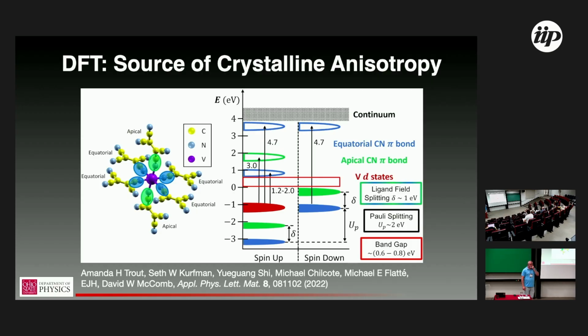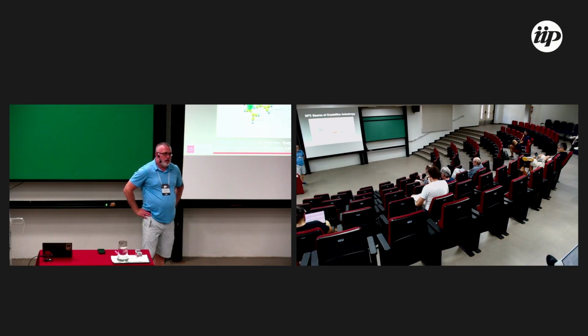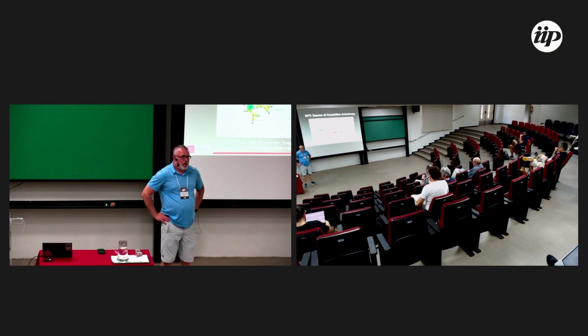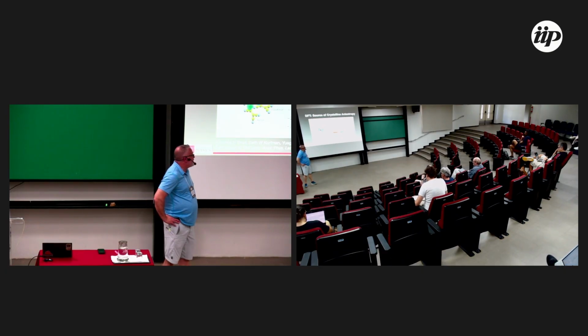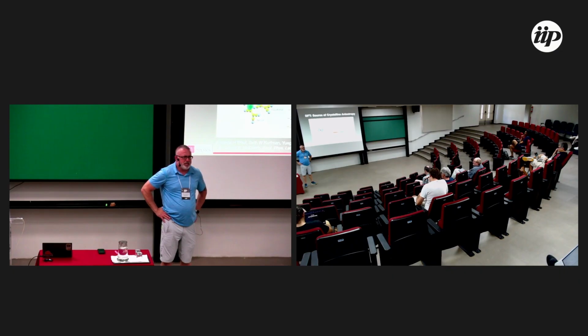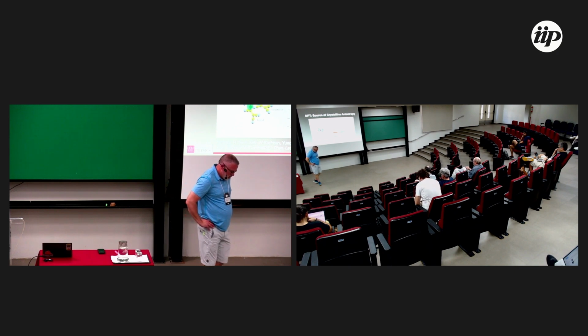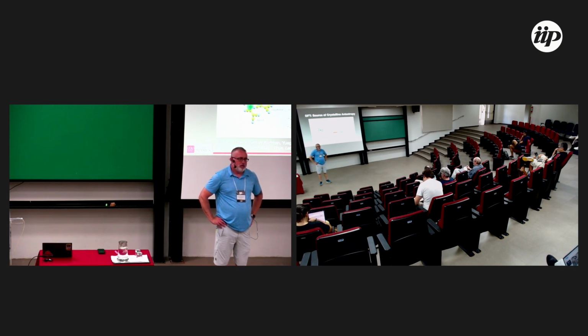Sorry, maybe one question related to this. So did you check if this is a g approximately equals 2 system? What is the g factor of this? Of the FMR? It's pretty close. I mean, the Ms is small, so the Kittel equation, the difference between that and a pure g equals 2 is modest, if that's what you're asking. Yes, I'm asking because I have only seen now angular dependent measurements as function of temperature, basically. So if you only have one frequency, then if the g factor would change as function of temperature, then the analysis is more complex, because then it's more difficult to disentangle basically Ms anisotropies and all of this.